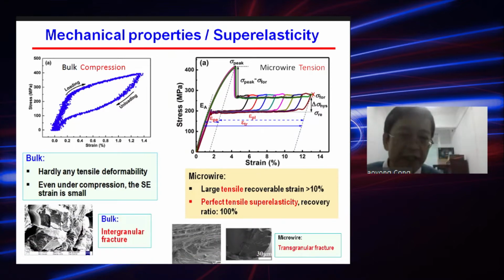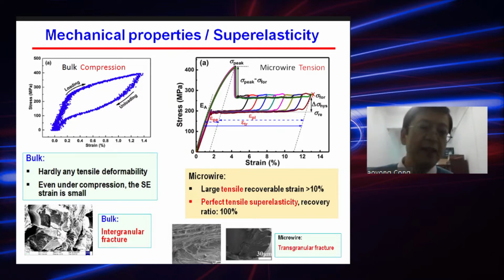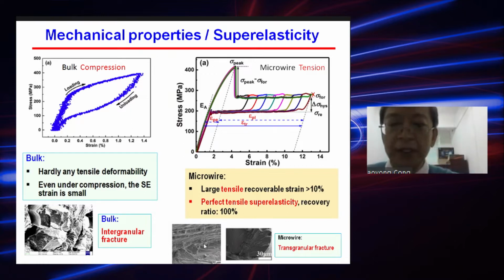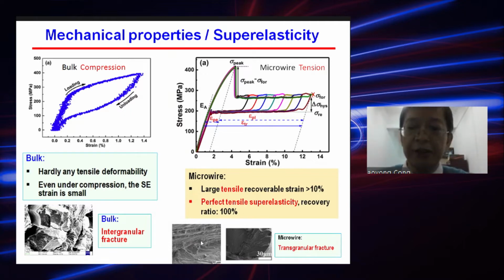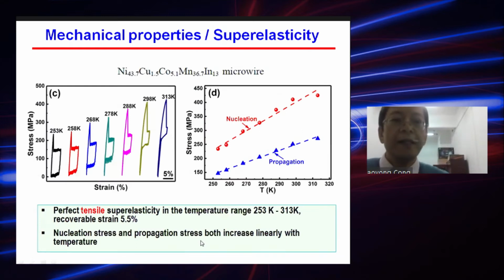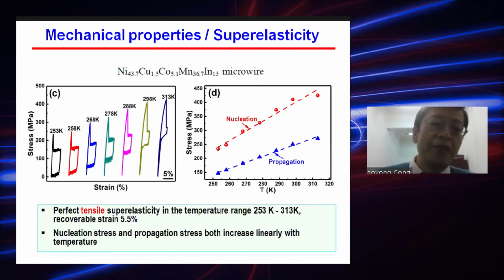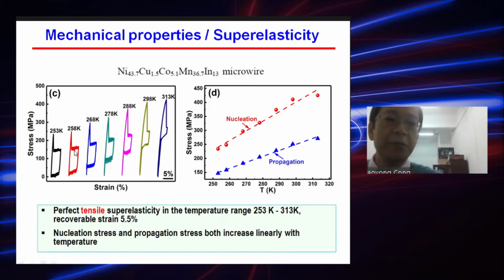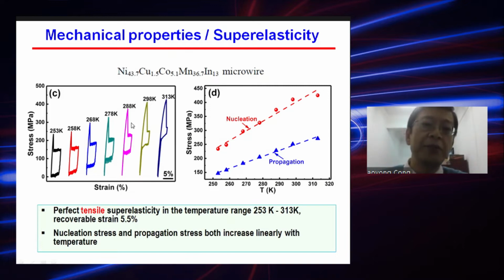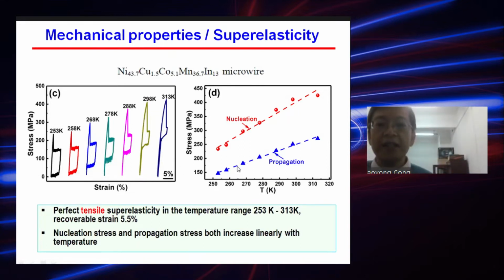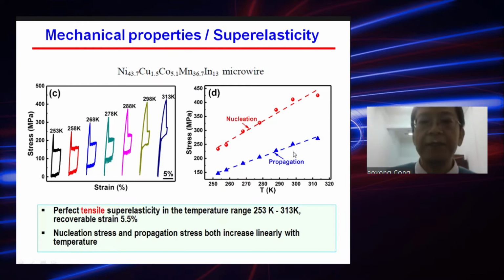We checked the fracture surface of the bulk sample. We see that it's intergranular fracture. For the microwire, the fracture mode is mostly transgranular fracture. This means the grain boundary in the microwire is not the weak point anymore. The fracture occurs inside the grain interiors in the microwire. And we checked the superelasticity at different temperatures. We find that we can get perfect tensile superelasticity at temperatures from 253 to 313 Kelvin, with a large recovered strain of more than 5%. And also the nucleation stress and the propagation stress increase with the temperature.